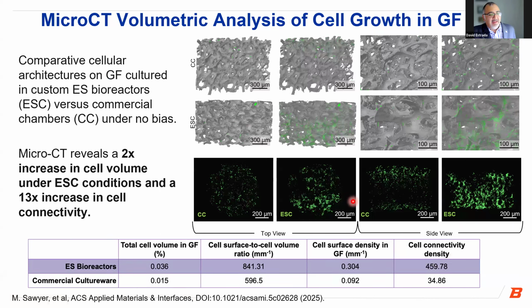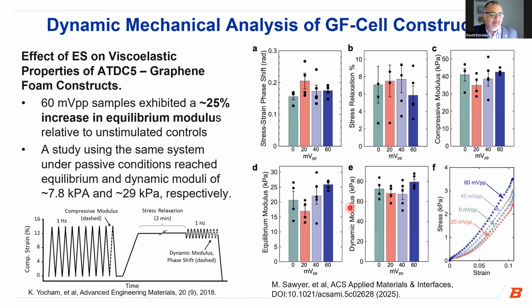So here are some of the key takeaways. You can see here just using commercial cultureware, the CC. We're looking at micro CT at different magnifications. And the green is the cells, right? And then this ESC is our custom chamber. And so immediately, without electrical stimulus, just submerging the graphene foam in the cell culture media, you can see that we increase the penetration of the cells throughout the graphene foam scaffold. So this is top view, and then this is side view through the center of that graphene foam. And so we get a 2x increase in cell volume under this chamber, but a 13x increase in cell connectivity, which is important for cell-cell communication as things start to differentiate, right? So just by holding the foam, we were able to get much better results.